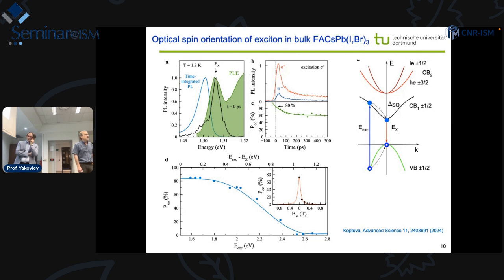At least I have in mind what you get from circular X-ray dichroism. You can split the atomic angular momentum into the orbital part and the spin part. So this is only an analogy. In our optical experiments, it typically doesn't come out. Maybe I'm not an expert in that, but at least with our methods, we never touched that. In the III-V semiconductors, you can really decompose them by light, by band excitation. One probably needs another laser, a far-infrared laser or synchrotron or X-ray lasers, that really touch this moment for intraband excitation. Maybe you have some information about some other experiment.